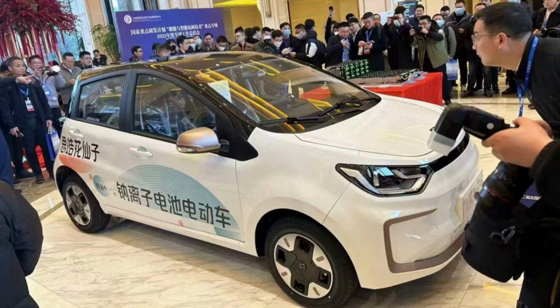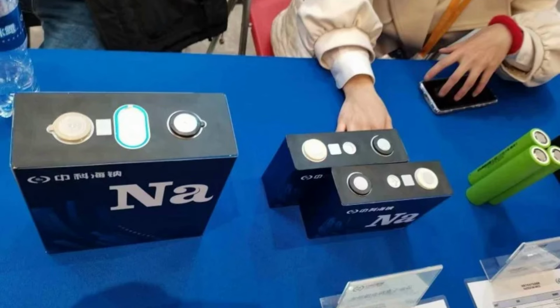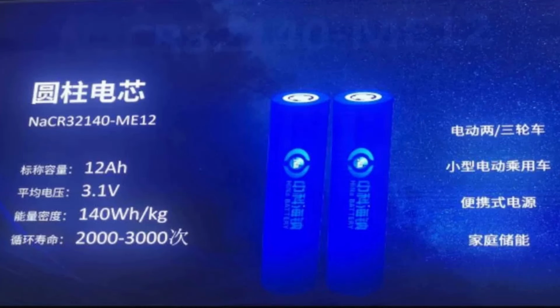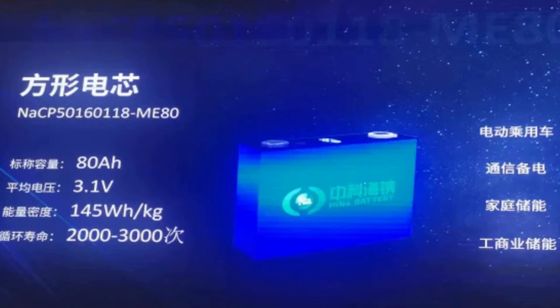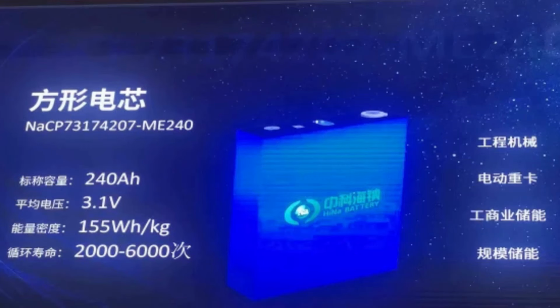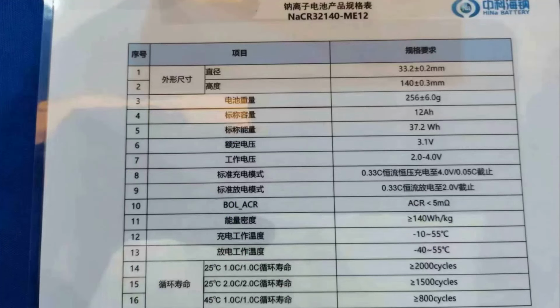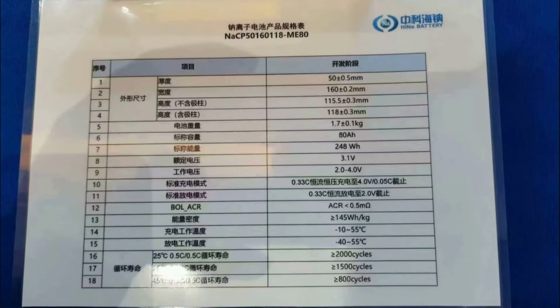HINA has 3 sodium-ion battery cells in the cylindrical and prismatic cell format. These cells have energy densities of 140 watt-hours per kilogram, 145 watt-hours per kilogram, and 155 watt-hours per kilogram respectively. The cycle life of these cells ranges from 2,000 to 6,000 cycles. They can be discharged to minus 40 degrees C and fast charged from 30% to 80% in 15 minutes. The cells use a copper-based layered oxide as the cathode and a coal-based amorphous carbon as the anode.